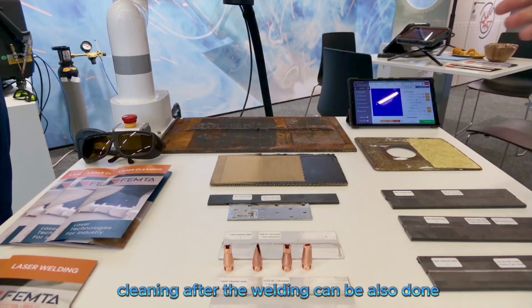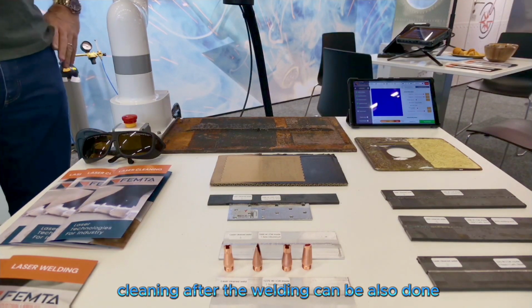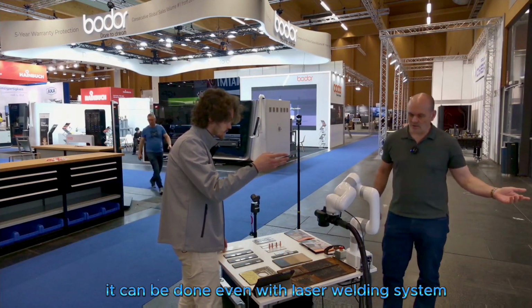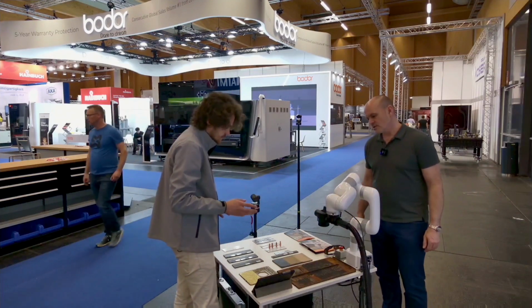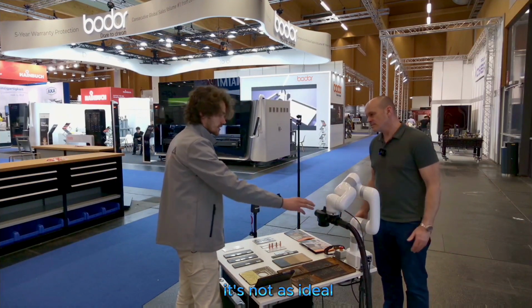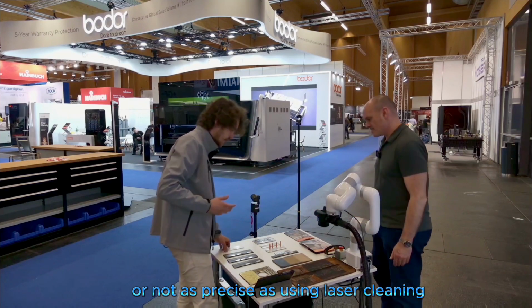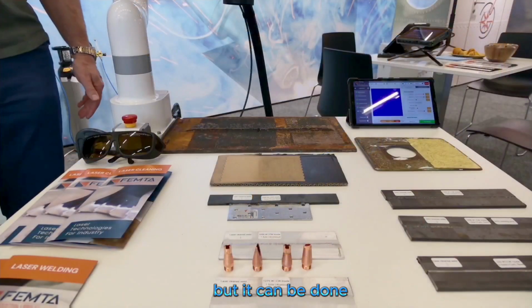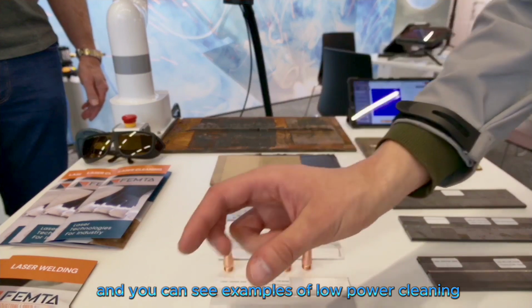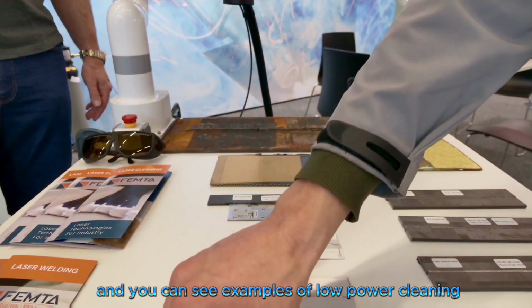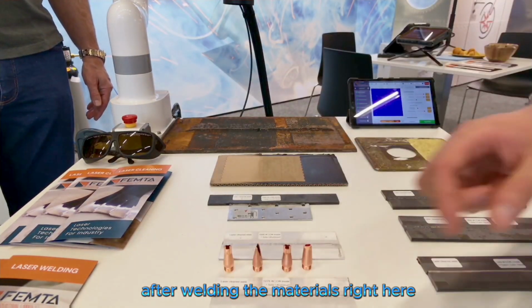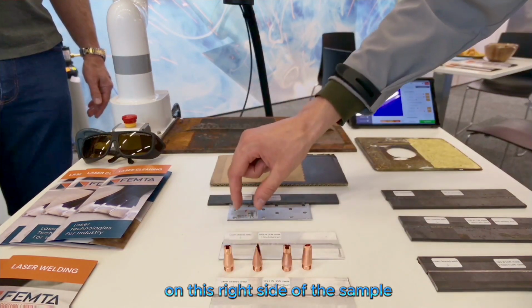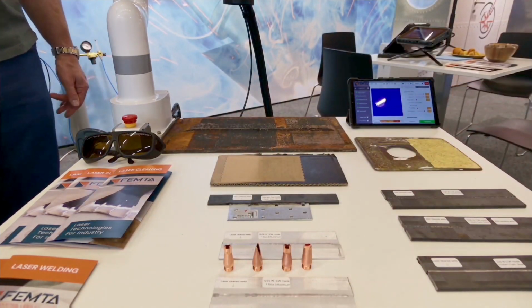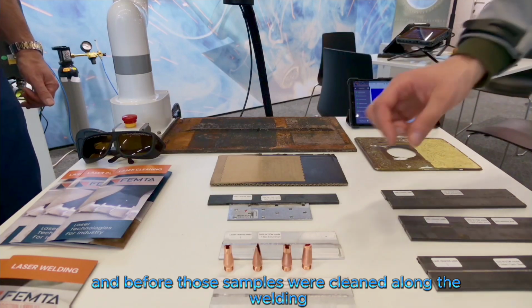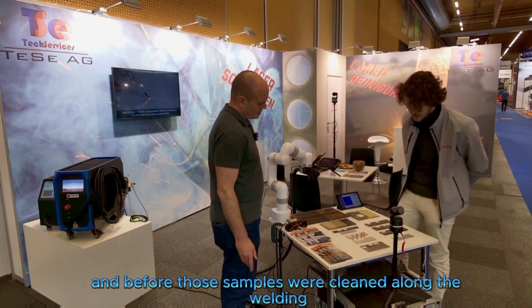Cleaning after the welding can also be done. It can be done even with the laser welding system itself. It's not as ideal or as precise as using a laser cleaning system, but it can be done. And you can see examples of low power cleaning after welding the materials right here on the right side of each sample. And before, the sample was cleaned along the welding beam.